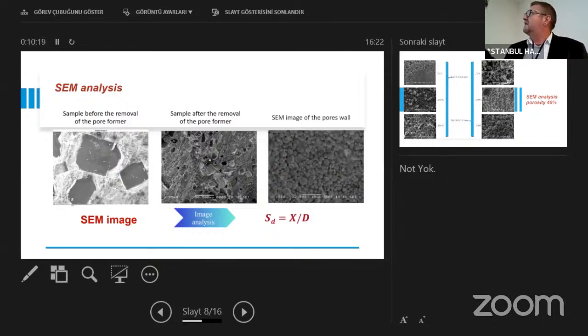We can see that sintering necks between the particles are there. It's okay. From these images of the pore walls, we measured the sintering degree as a ratio between the sintering neck and the particle's diameter, considering similarly sized particles.